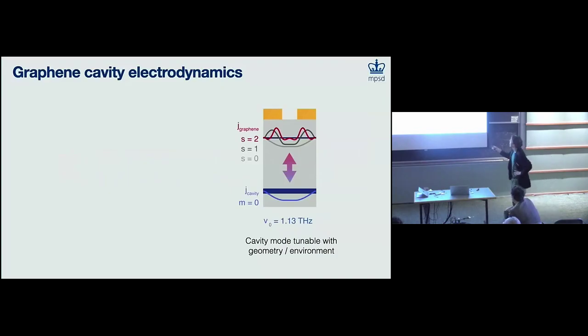So we're now going to look at a full heterostructure, and this is the simplest possible heterostructure, monolayer graphene, encapsulated in HBN, sitting on top of a graphite gate. One thing I should point out is the plasma frequency of these graphite gates. These are 2D plasmons, so we can tune the frequency with dielectric screening. So basically, the farther we move this away from the sample and the metal waveguides, the higher the plasma frequency gets. So for this device, we've intentionally parked the plasma frequency at fairly high frequencies outside of our experimentally detectable bandwidth. And the reason we did this is we wanted to see what the graphene electrodynamics will do without this cavity mode sitting in the middle of our bandwidth.